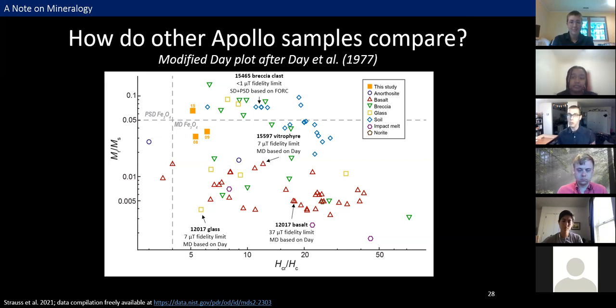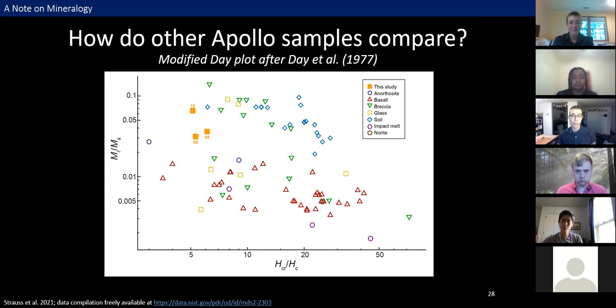However, there's a problem when we start to look at the domain states from which, again, grain sizes are often inferred, which is those dashed lines do not actually exist. The guiding domain parameter ranges were originally developed for magnetite, Fe3O4, and not only are they not applicable to other types of magnetic minerals, but studies of terrestrial minerals in the last few years have shown that they were likely fairly imprecise tools in the first place. So we'd rather not encourage overinterpretation of our actual data based on those ranges.